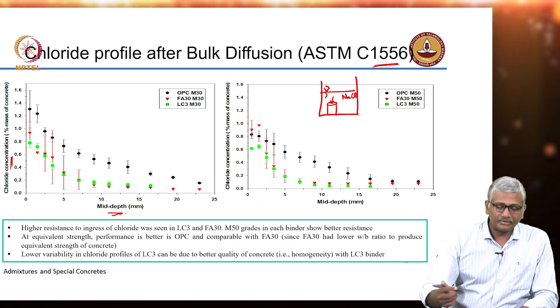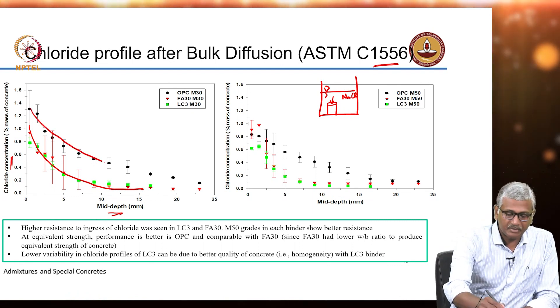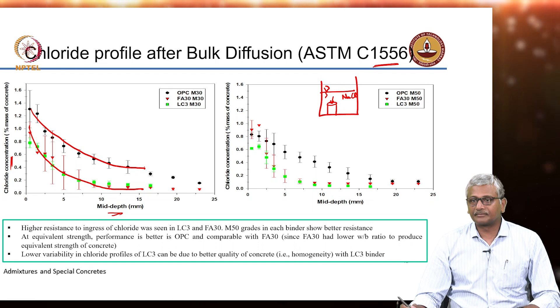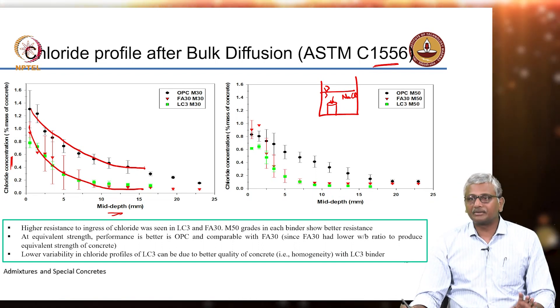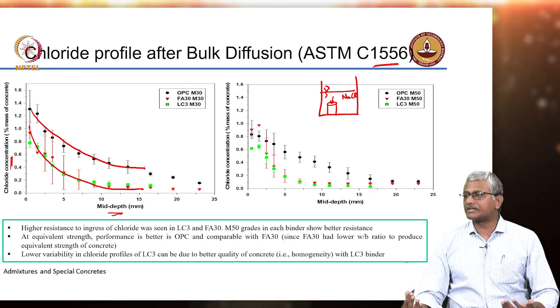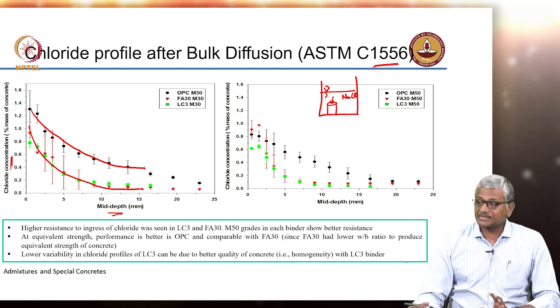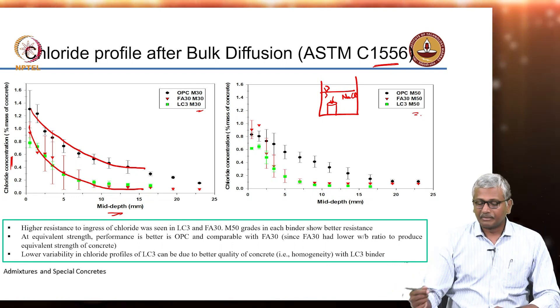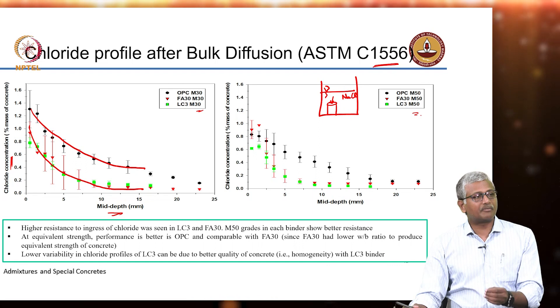The chloride profiles are clearly much lower for fly ash and LC3 based systems compared to OPC. One important difference from the ASTM standard is that all these concretes were cured for one full year before chloride exposure, giving sufficient time for completing potential hydration. Any negative impacts of fly ash at early ages would have been overcome with such extended curing. Very clearly, LC3 and fly ash based mixes show distinctly better performance at equivalent strength levels M30 and M50.